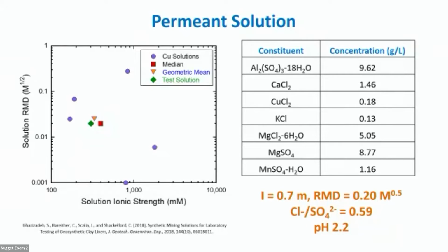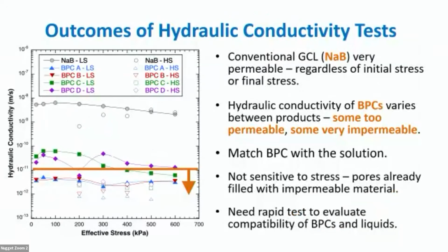It's sulfate predominant. The anion ratio of chloride to sulfate is about 0.6, and then it's acidic as we'd expect. It's pH 2.2. And we ran these tests, as I indicated. We started these about 2 years ago. Most of them took about a year, some took up to 2 years.